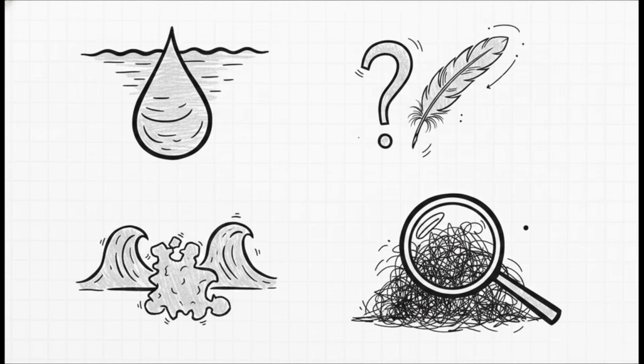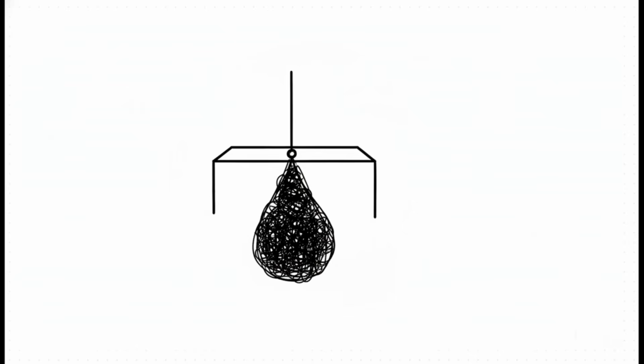First is the interaction volume effect. Second is its serious struggle with light element detection. Third is the really frustrating issue of peak overlap. And fourth is its relatively high detection limits for trace elements. Let's directly contrast our first superpower with our first limitation. You have high spatial resolution from the electron beam, right? That lets you target a tiny nanoparticle right on the surface.